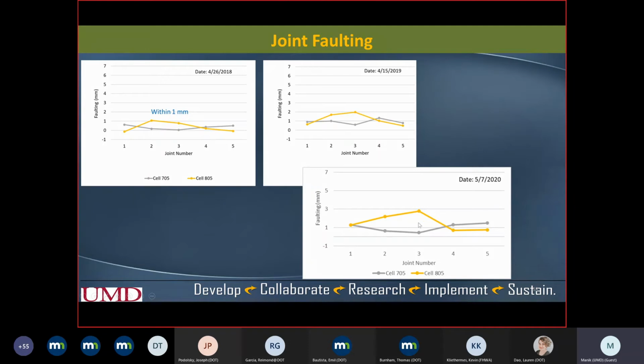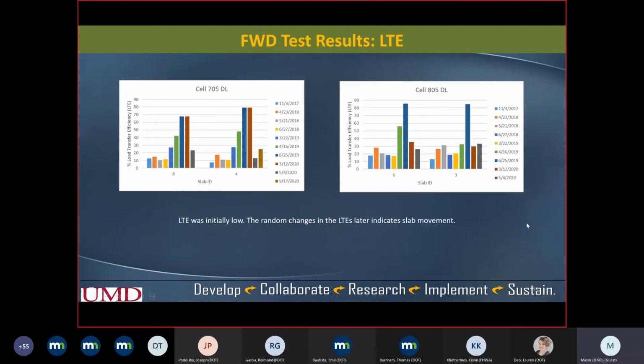These are overlays on geofabric, so we saw less faulting. When you look at the FWD test results, initially you can see the load transfer efficiency was low for both cells. Then it changed randomly, or I don't know if there is any pattern, but some dates showed really high load transfer efficiency, at least on the joints where the LTE was measured. So LTE was initially low. The random changes in the LTE later in life indicate slab movement.